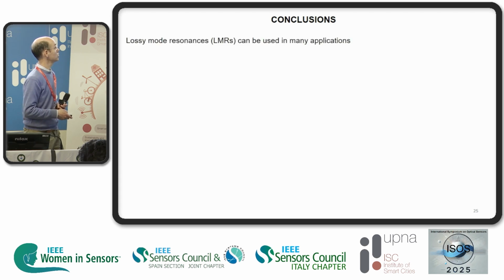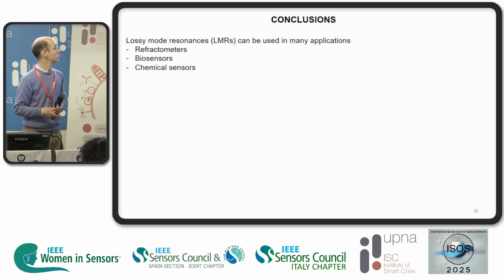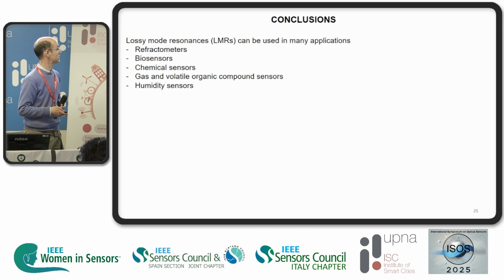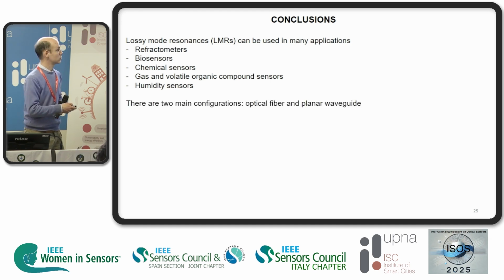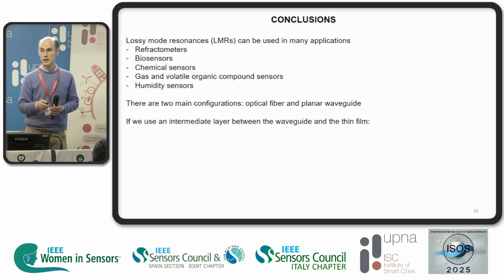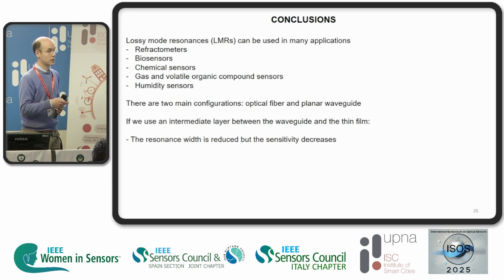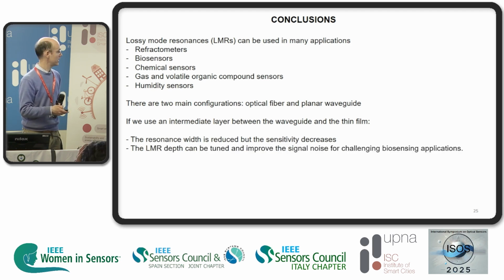So some conclusions. Lossy mode resonances can be used in many applications: refractometers, biosensors, chemical sensors, humidity sensors, gas and volatile organic compound sensors. There are two main configurations: optical fiber and planar waveguide. And if we use an intermediate layer, the degrees of freedom increase and the resonant width is reduced, but the sensitivity decreases, so we must improve that in terms of figure of merit.